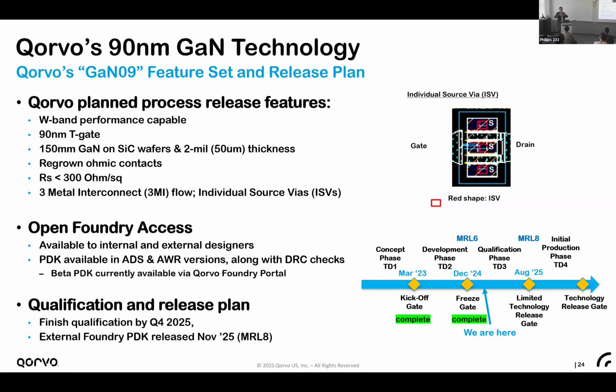among different fingers, because once we want high power from these devices, we need multiple fingers to increase the device width, the effective width, to generate more power. But as we have more fingers, it's harder and harder to connect or ground those sources in the middle of each finger. That's why we need vias located just between these fingers to get them connected directly to the backside metal. So these vias, compared to the silicon world, are at a much larger size. In silicon, you may be looking at micron or even sub-micron size right now.